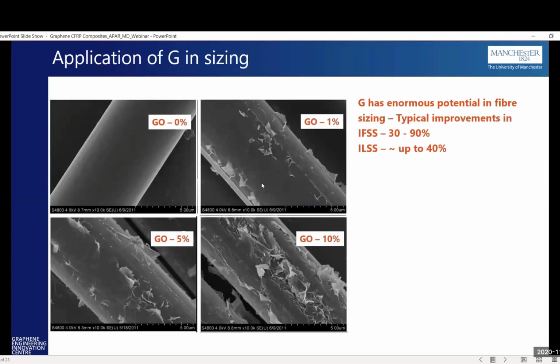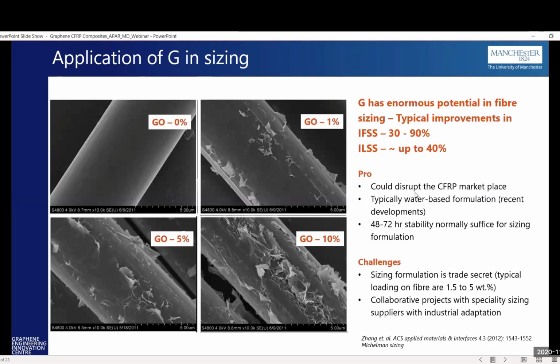So another area is graphene to be used in the sizing itself. Graphene has enormous potential in the sizing industry, and typical improvements that you can get are up to 40% on the interlaminar shear strength. It's quite compelling for a lot of industries. The advantage is that it could actually disrupt the market.